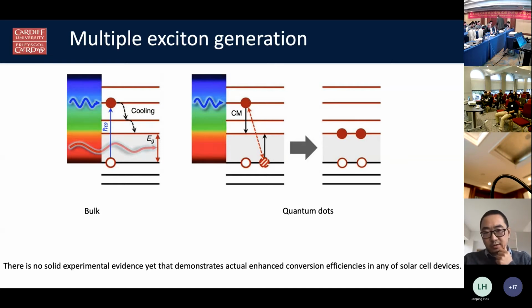In terms of quantum dots, they have an advantage because of the quantum confinement effect. So the cooling rate is largely extended. It means you have enough probability to use this high energy electron to excite another pair or even two more pairs of electron holes. That is what we call the multiple exciton generation phenomenon.